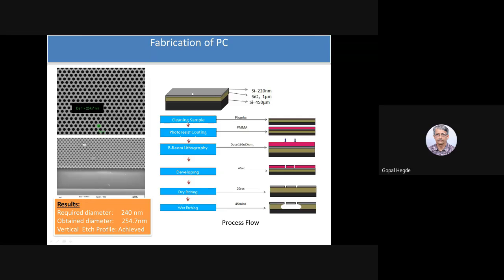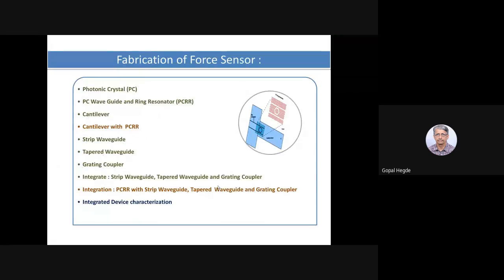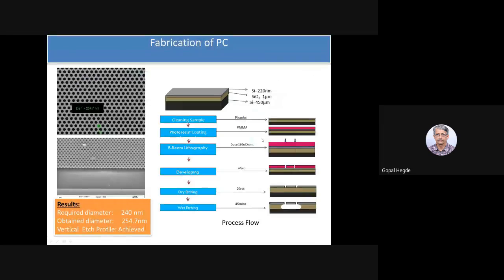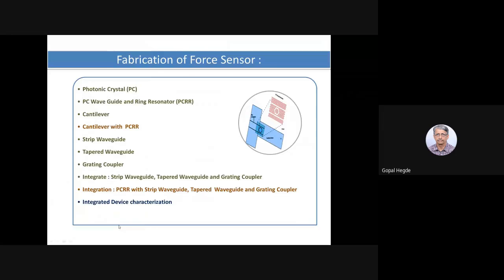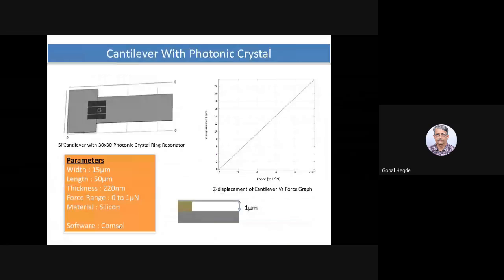The entire thing was fabricated on an SOI wafer, and the process flow was very difficult. You can make this structure, but again the challenge is to launch light into these waveguides. The entire structure is about 200 microns. The cantilever length is around, I'll give you somewhere here.